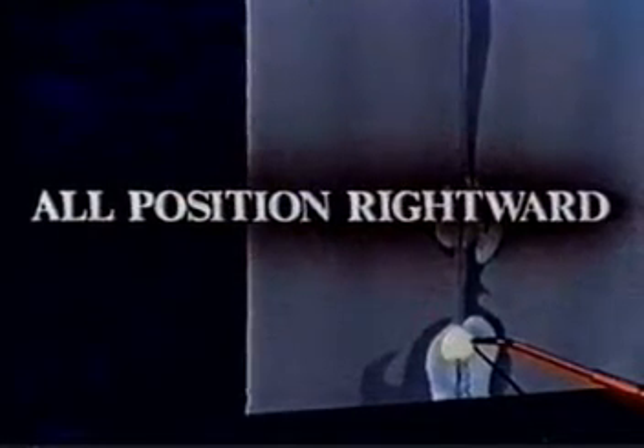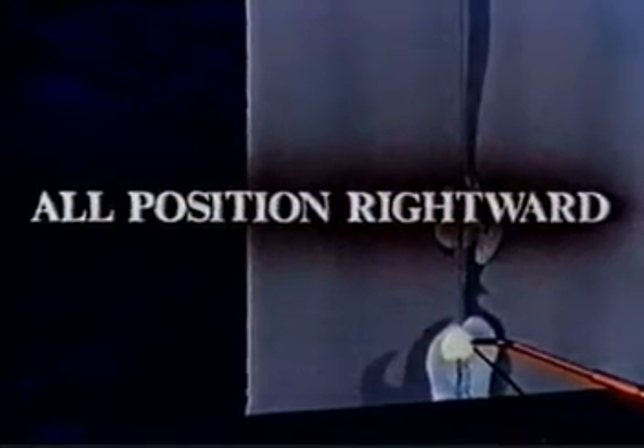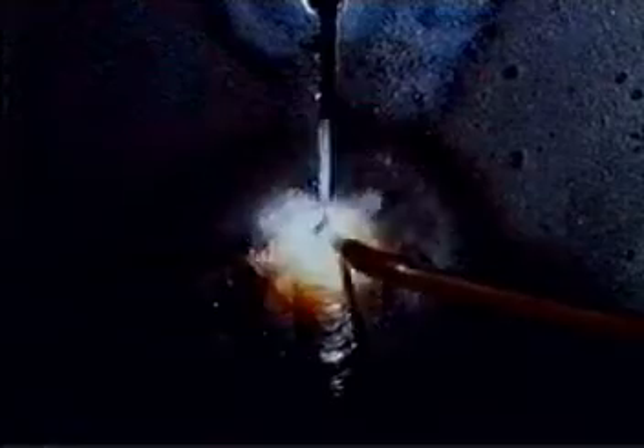All position rightward is another way to tackle a vertical weld. Hold the rod at an angle of 20 degrees from the blowpipe and the blowpipe at 90 degrees from the weld with the tip of the cone just clear. By directing the flame at this steep angle, the square edges are melted rapidly and the pull of gravity makes the molten metal form the weld pool into which the filler rod is fed. It's important to keep the pool as short as possible.